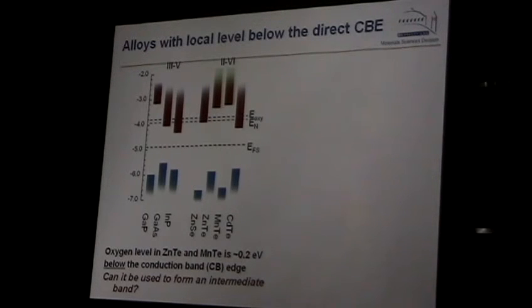Now, of course, we had a material which we thought was an intermediate band material, but not exactly, because our intermediate band was still too broad. So we looked at the potential candidates for our intermediate band material, and you can survey this relatively easily. Basically, again, you put your materials on the same scale with respect to the vacuum level. So you see the conduction band edges or electron affinities of different materials: indium phosphide, gallium arsenide, gallium phosphide. The gallium phosphide has the smallest electron affinity. And then you have the valence band here.